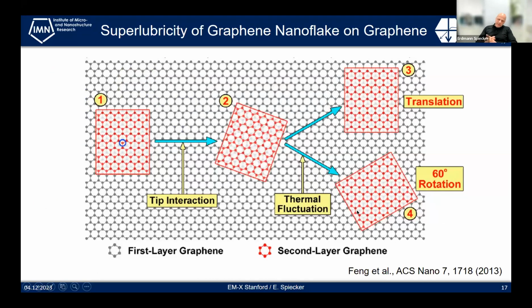There's another very nice work where monolayer graphene flakes were moved with the AFM as well on top of a graphene, and they observed when the graphene flake rotates from the locked-in position or orientation, then the sliding friction was reduced considerably, but then after a while it was locked in again due to thermal fluctuations. And our idea was not now to do a similar experiment, but in the TEM to see what's going on at the interface and what type of defects are involved.